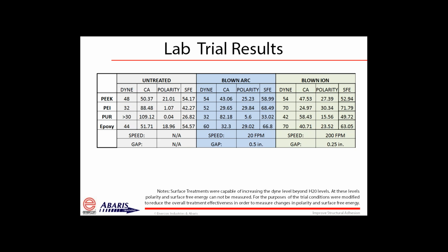So we then took these and also looked at a few more unique or more advanced materials, PEEK, PEI. And what you'll see on these materials is that not all of them were as low on the dyne level as they started with. Some of them had a low contact angle under 90. You see that with the PEEK and the epoxy levels here. Well, when you apply blown arc and blown ion technologies, you see these dyne levels again increase. The contact angles are decreasing as well, and the surface free energy increases as well.